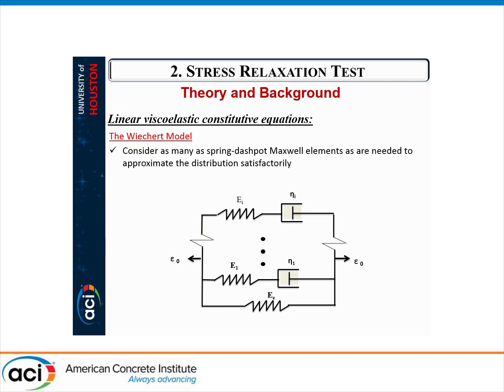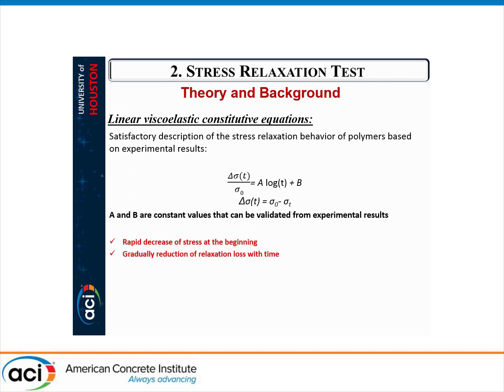Also, more complicated models have been developed by including more elements in the system, but we have to notice that the more complicated the model is, the better and more realistic results we get, but we have to consider a lot of effort to define the material characteristics of each element in the system. However, by experimental studies, relaxation in FRP composite was found to be linearly related to the logarithm of time. As presented in this equation, the constant values A and B can be obtained from experimental results by regression analysis.